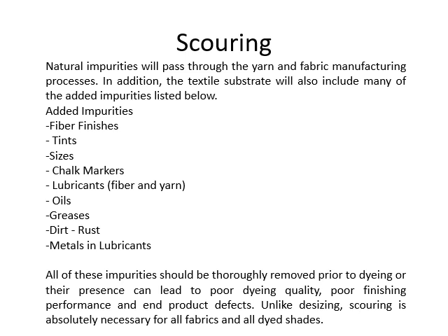Residual oils left on the fabric can degrade during storage, resulting in fabric yellowing. Additionally, degrading impurities can also result in the formation of noxious fabric odors. The effectiveness of a scouring process is normally evaluated using a laboratory method which involves extraction of residual oils, greases and dirt. The amount of residual materials extracted is correlated to the degree of cleanliness of the substrate.